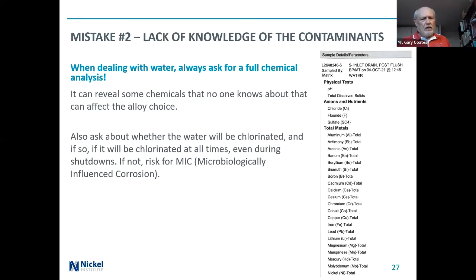And on top of that, if the water is going to be chlorinated, we want to know that, and if it will be chlorinated at all times, even if the system is shut down and if it's not drained, because we're really worried about microbiologically influenced corrosion there too. So most corrosion tables won't even mention MIC corrosion, so it may not be top of mind when you're thinking about it. But if the water is supposed to be chlorinated, but may sit there for a long period of time, the chlorination disappears with time. Microbes can grow and cause corrosion of stainless steels.